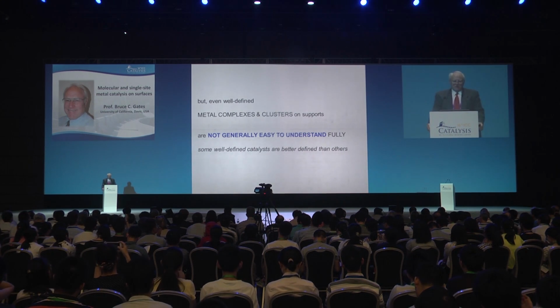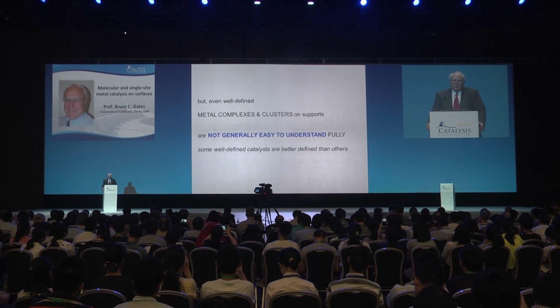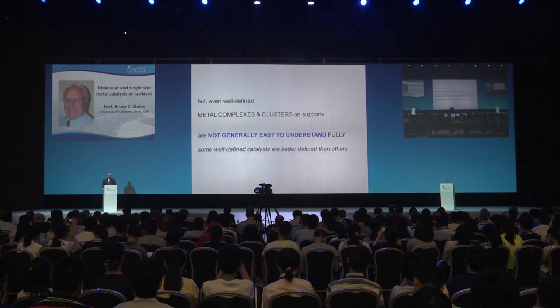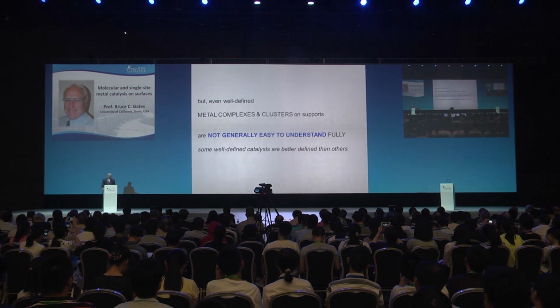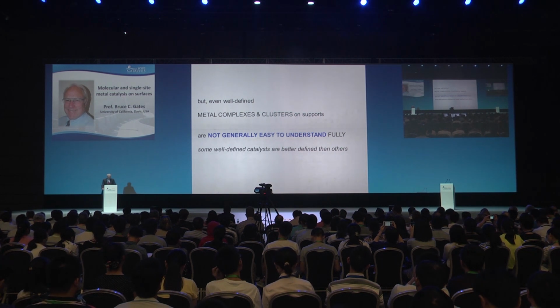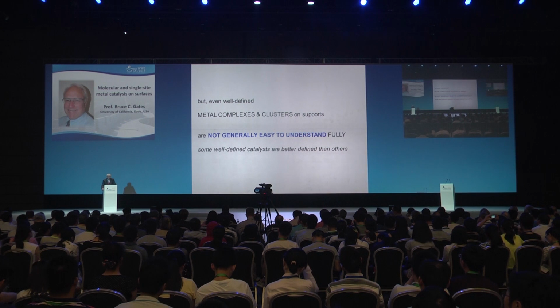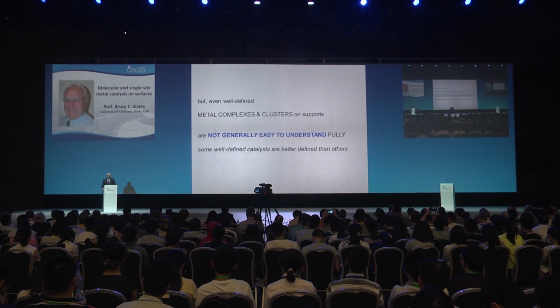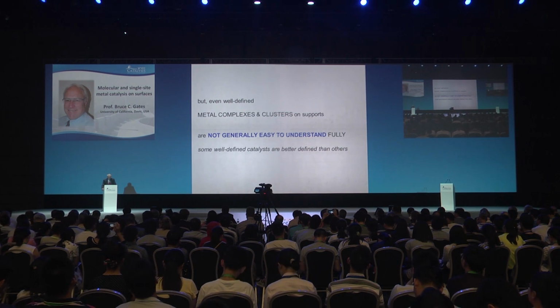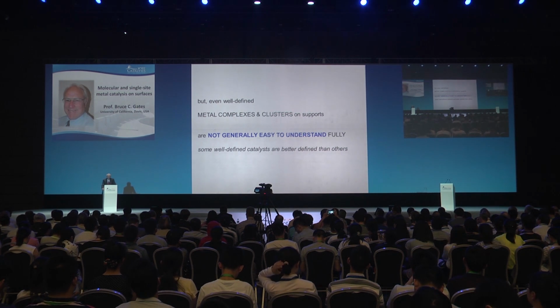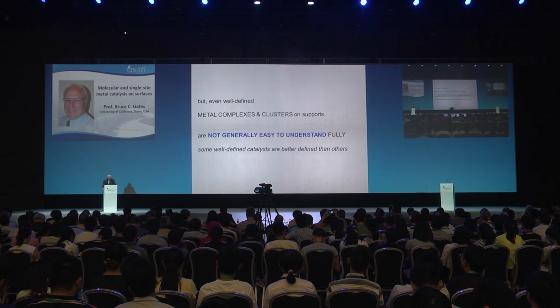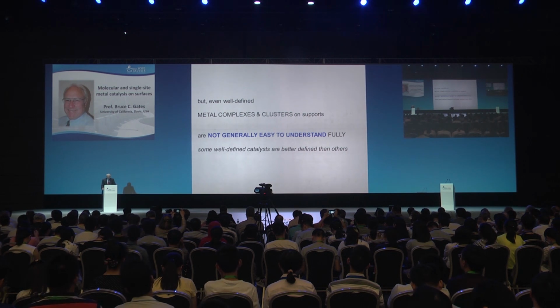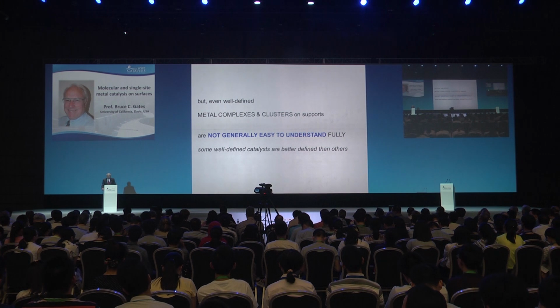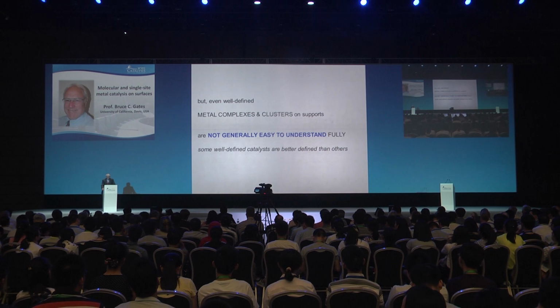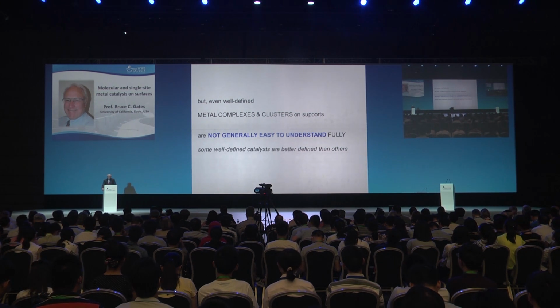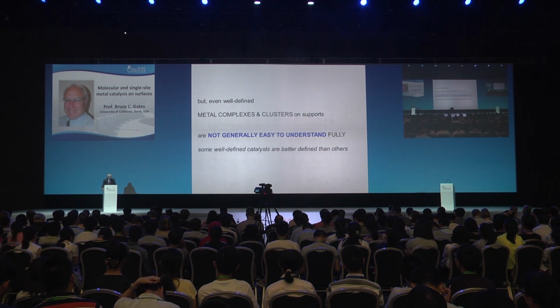And I want to emphasize this again. The typical supported metal complex catalyst is not easy to understand. The Phillips catalyst for ethylene polymerization has been investigated for decades by lots of extremely good and well-equipped scientists, and they still don't understand well quite what it is or how it works. So there are catalysts that on the face may appear to be simple, but really aren't. And the other point I want to emphasize is that lots of us have been using the term well-defined supported catalyst for years. Please be careful. Some well-defined catalysts are better defined than other well-defined catalysts, and we're looking at a moving target and looking at a field that's developing rapidly.